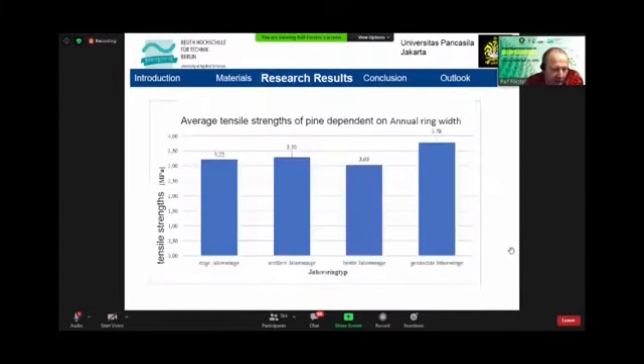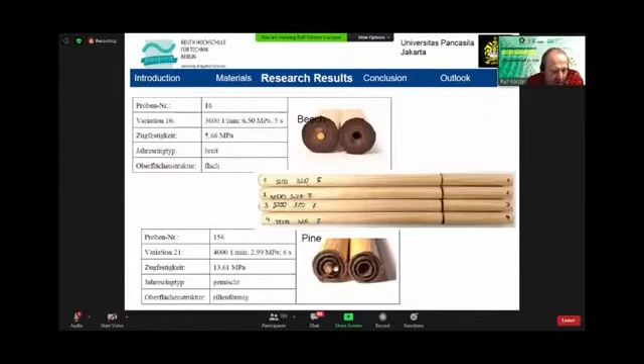What is a very interesting result, we have different results depending on the thickness, the width of the annual ring of wood. This is not independent from the structure of the wood. That's a very interesting result that we have an influence of the inner structure depending on the ring width in the wood structure. So here, can you see?